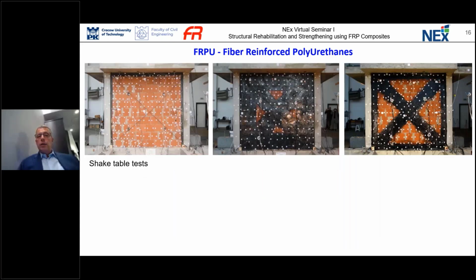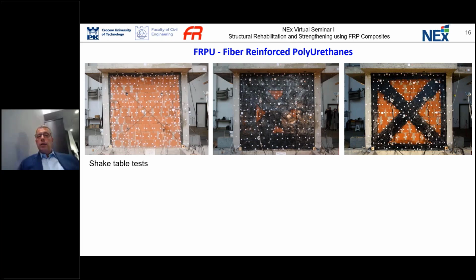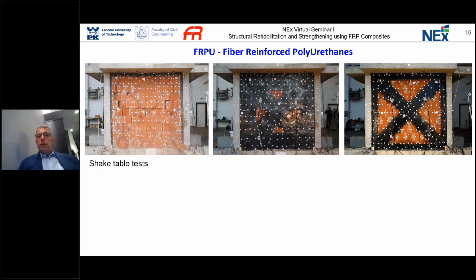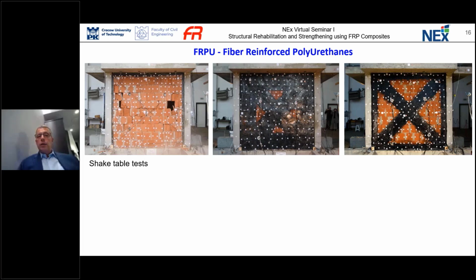So I would like now to present you some cases and movies from this shaking table. Mainly on the left hand side, you can see the masonry infill wall. It is protected here in other type of flexible bonding, but let me show you how it works. So you can clearly see that the structure is losing its stiffness, and finally at the end of this test it was not collapsed due to protection with polyurethane flexible bonding and the interface between masonry and reinforced concrete structure, but the global stiffness was lost from 100% down to only 6%.